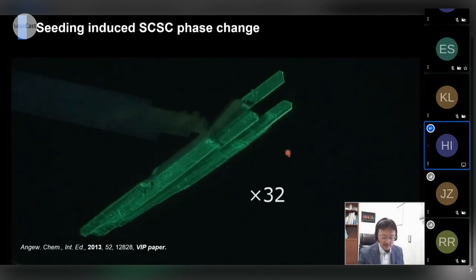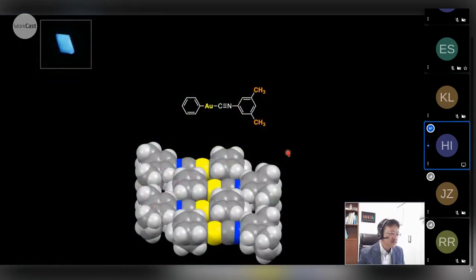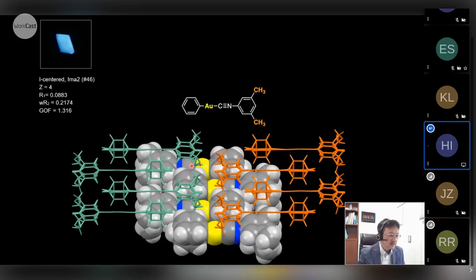This is very interesting phenomena for these crystals. This is a crystal structure after the phase change. This can show the blue luminescence. And the crystal structure is very different from some previous one. The complex was situated as maybe layer-like structures. So this is one layer, and the next layer is onto the top part of this layer.